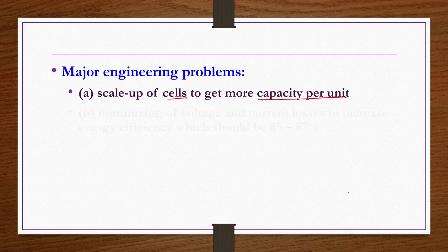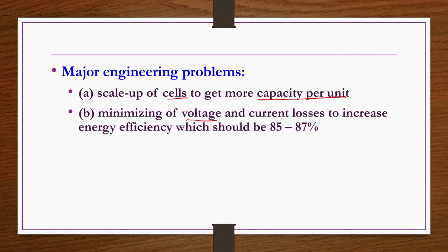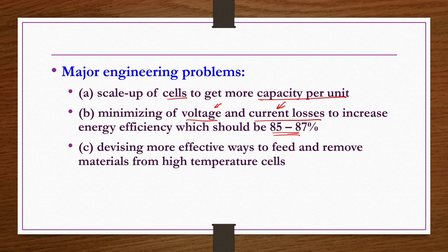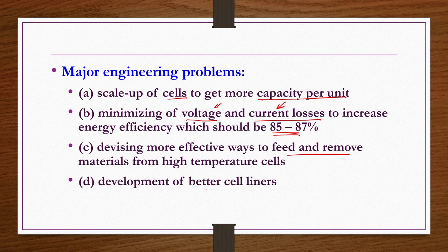Major engineering problems of this process, if you see: scale up of cells to get more capacity per unit is one important issue. Then minimizing of voltage and current losses to increase energy efficiency is another issue. Because minimum energy efficiency should be 85 to 87%, that efficiency may be improved if you reduce the loss of voltage and current. Okay. Devising more effective ways to feed and remove materials from high temperature cells is another issue, and then development of better cell liners as well. Only graphite liners we have seen, so better cell liners could be more beneficial.